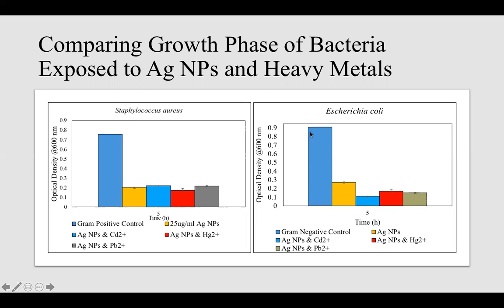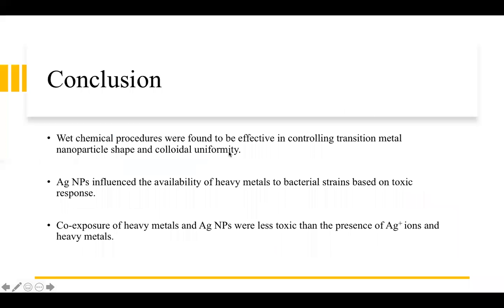And in the presence of E. coli, same kind of concept that we see here. There's a slight change in how they grow, but we do still see the same patterns, that they become more similar to silver nanoparticles and the elements than their control groups alone.